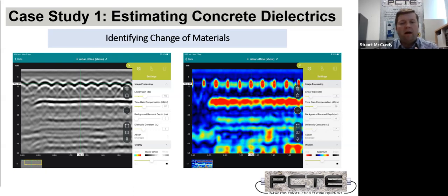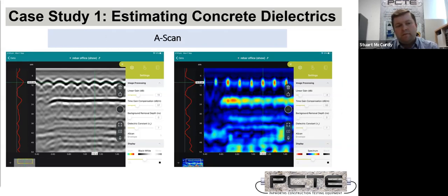In this scan I just started with an estimate of 7 for dielectric, which would be average for concrete. And I just hit somewhere on the screen. I brought up a crosshair. I found a bar at 1.12 meters from where I started, and my depth estimate was around 102 millimeters. That's not the best way to pick a point, because you have this red dot, or on the left-hand side, you have a white, a black, and a white line. So where within that dot is actually the change from concrete to steel?